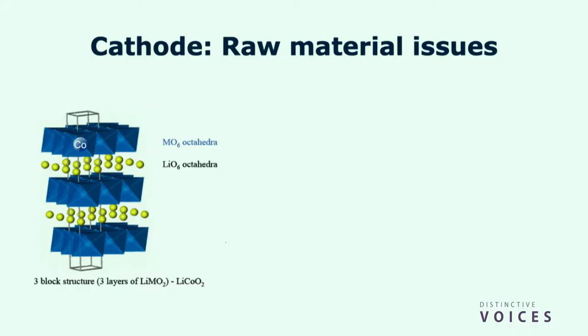Or let me answer how good the current state-of-the-art cathode can be. As I mentioned, lithium cobalt oxide was the invention that led to the lithium-ion battery. So, cobalt surrounded by six oxygens, lithium. Cobalt's problematic for the reasons I said. If you put nickel in there, it's cheaper and can increase the capacity. But nickel has this propensity to migrate into the lithium channels, and it plugs up the lithium channels. So if one can put a little manganese in there and the right cobalt, one can prevent that nickel migration, and that can improve your performance.